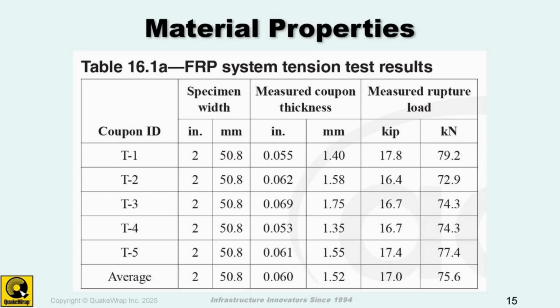So in this particular example, they have a thickness that varies from the smallest one being 0.053, and then the thickest one being about 0.069. And you can expect this kind of variation on a sample because it's done by hand in the field. So this is kind of normal.